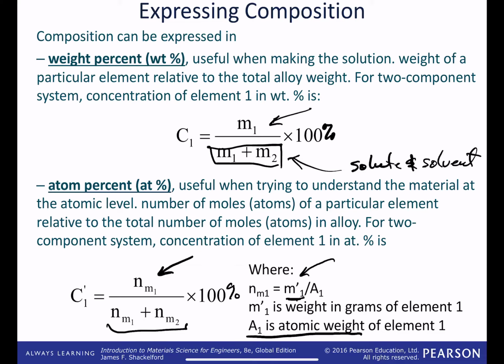And in the latter, actually counting by mole or by atom can be very useful for understanding things like some of the energetics involved in asking one atom to substitute for another, because often that is normalized per atom site or per atom solute rather than by the characteristics of having the mass, which is the option up here. So counting by atom percent is often more useful when we think about energy for creating some of these substitutional solid solutions.